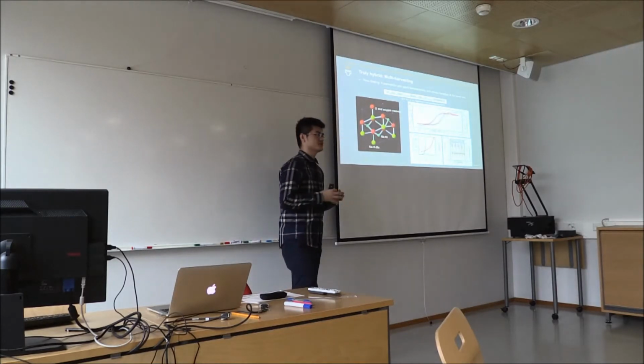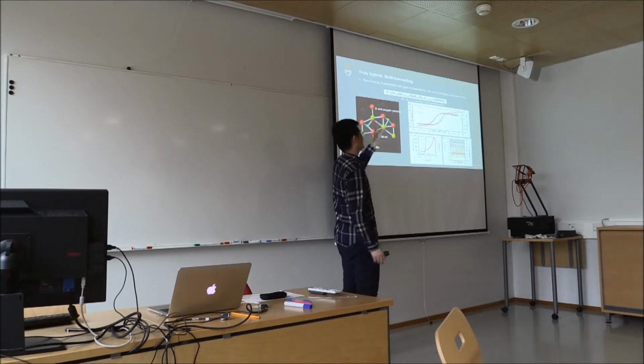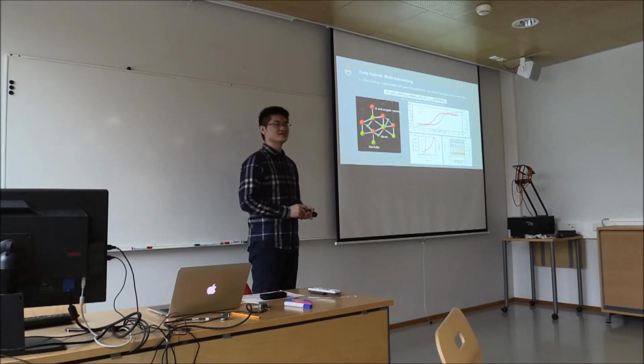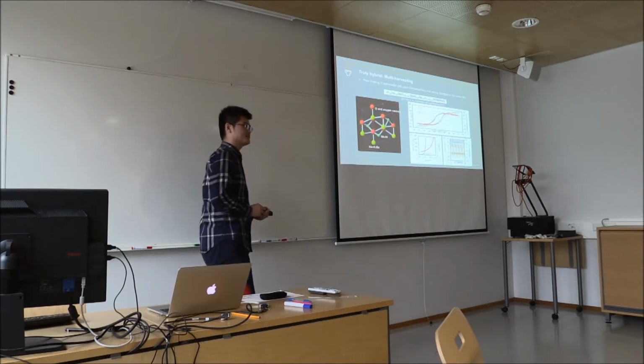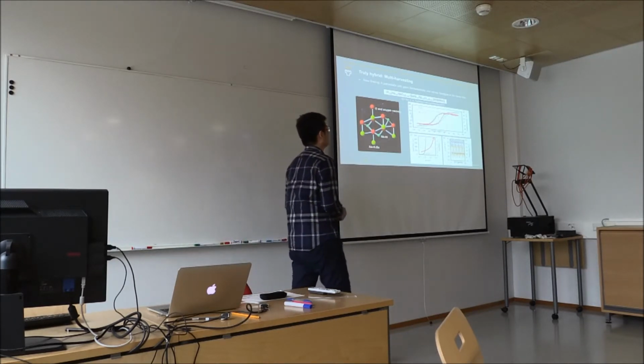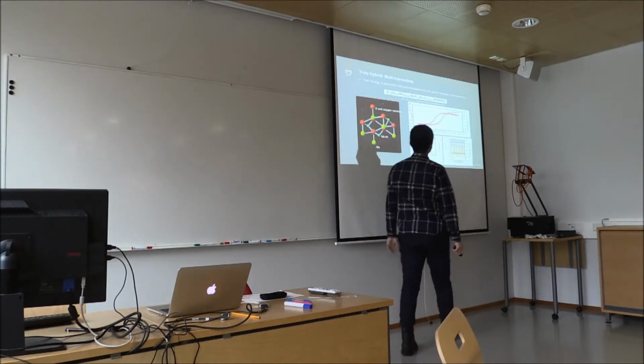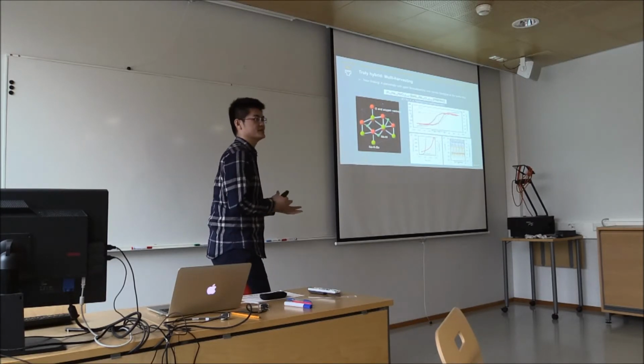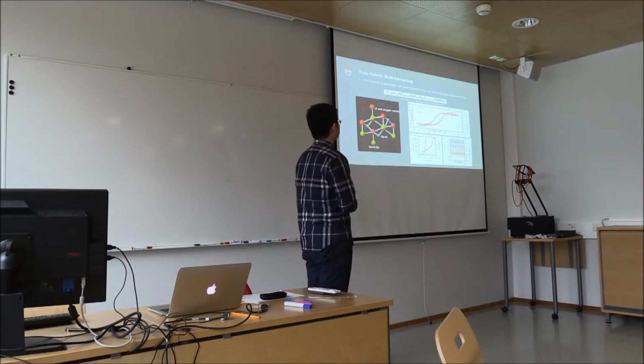But fortunately, I got something out of this simple ABO3 structure. It's based on KNN. KNN is a very widely used lead-free piezoelectric material nowadays. Some company, I think, already has it in practice, but I'm not so sure. But yes, KNN is the most researched lead-free piezoelectric composition. And we use the same principle to introduce some oxygen vacancies here. But the amount is very, very small. The oxygen vacancy concentration is just 0.17%. But we got very promising results, very promising.